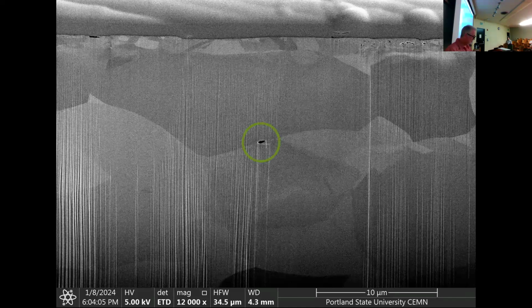And here's a little bit of a close-up. So if we wanted to turn this into a TEM lamella, this is a different sample. We would simply cut a pocket on the backside, attach a manipulator, lift it out, and weld it to a TEM grid. And here we can see this is a metal sample. I'm not sure what metal it is. I think this was steel, if I remember right. And that's pre-thinned. It's not clear to the thickness that we would need for doing STEM on it or transmission EBSD. But I didn't want to go all the way there. This is from an old demo that we'd done.